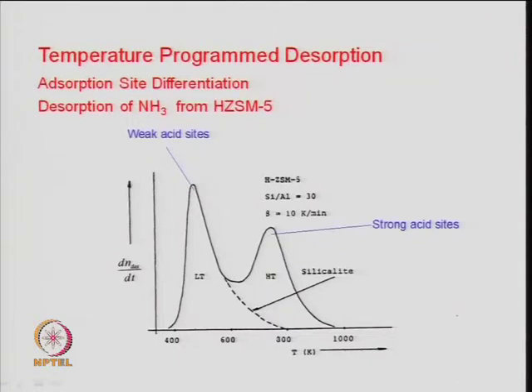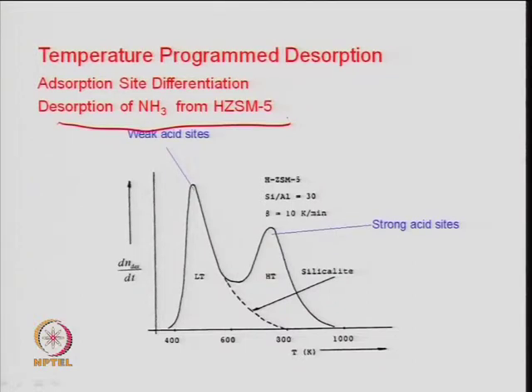This is a typical graph obtained during TPD — the desorption of ammonia from the HZSM-5 catalyst. First, ammonia is allowed to adsorb under given conditions, then flushed with inert gas so that superficial ammonia is removed, and then a heat treatment is given to the sample. It can be done in the form of pulses — give a pulse and heat the sample; once adsorption is over, heat it and at different temperatures you will see peaks in the detector.